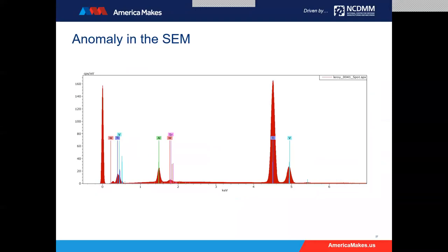The x-ray spectrum peaks line up pretty well for tungsten and strontium. Tungsten makes a lot more sense for what would be in there, since the atomization tips for making the powder are made out of tungsten carbide. We assume a piece of that flaked off somewhere in the atomization process. This information can be passed back to the researchers to see if having tungsten in the microstructure is going to be an issue compared to other elements.